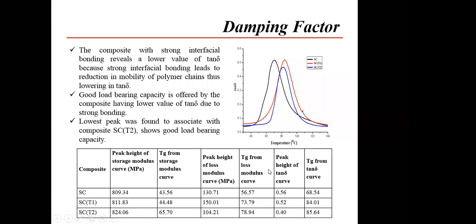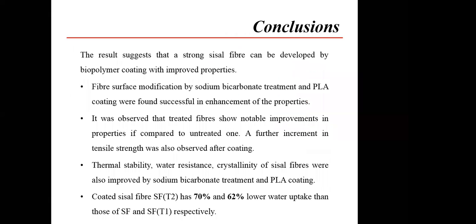Damping factor, tan delta, is defined as the ratio of loss modulus and storage modulus. So there are three parameters which are temperature dependent and provide information about the interfacial bonding between the fiber and matrix. So basically, DMA, dynamic mechanical analysis, also predicts the effect of time and temperature on polymer viscoelastic properties under different environments. These are some conclusions.